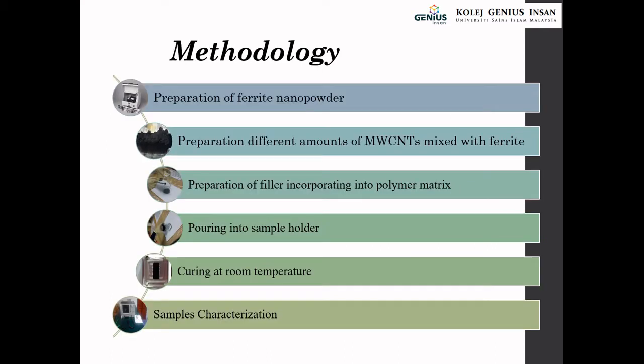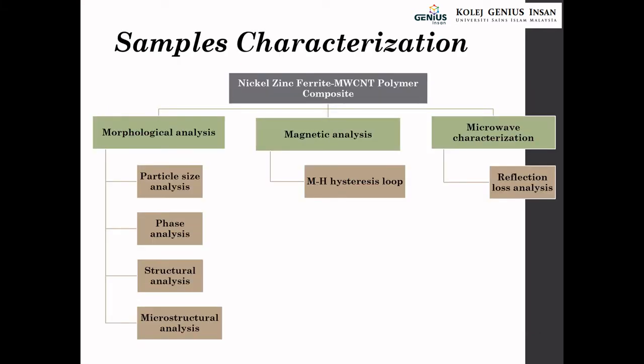For the methodology part, we prepared ferrite nanopowder, which is nickel zinc ferrite, by milling it using high energy ball milling for 10 hours. Then we prepared different amounts of MWCNT mixed with ferrite, from 2 weight percent of MWCNT until 6 weight percent. The filler was incorporated into a polymer matrix, poured into a sample holder, cured at room temperature, and finally sent for sample characterization. For sample characterization, we do morphological analysis, magnetic analysis, and microwave characterization.